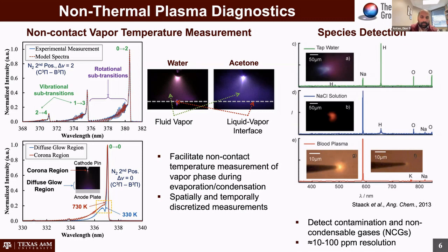And so we do this microplasma induced breakdown spectroscopy. In a sense, breakdown not to the level that you would see in LIBS systems, where you actually damage the material that you're measuring, because the LIBS makes a thermal plasma. Here, your non-thermal plasma is low enough energy that all you see is detection of species. And by counting the photons through a spectrometer and, say, for example, a photomultiplier tube, we can actually estimate the concentration of that particular element or molecule or radical in the system that is emitting light.